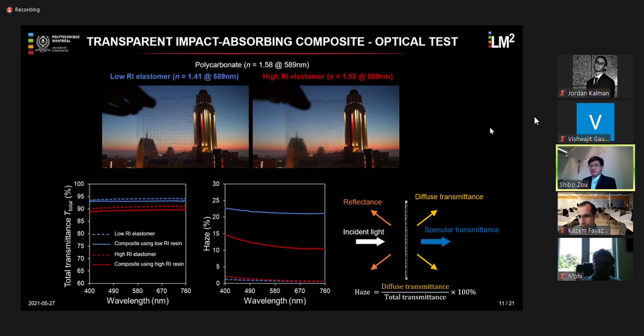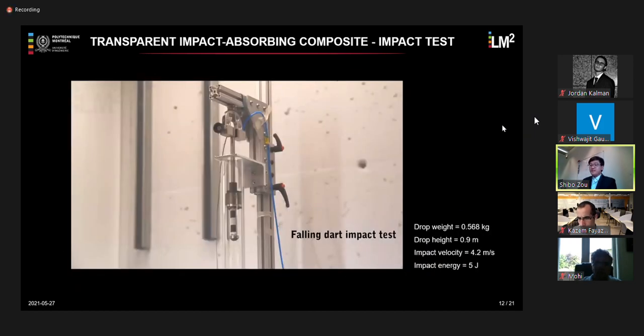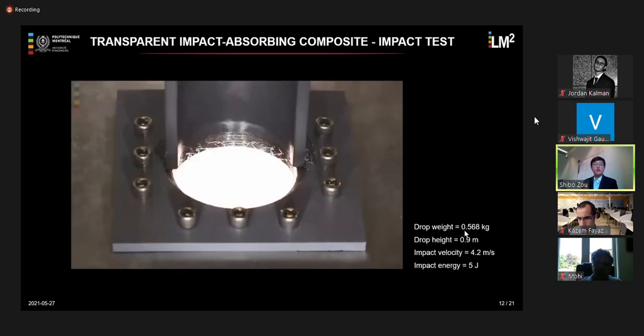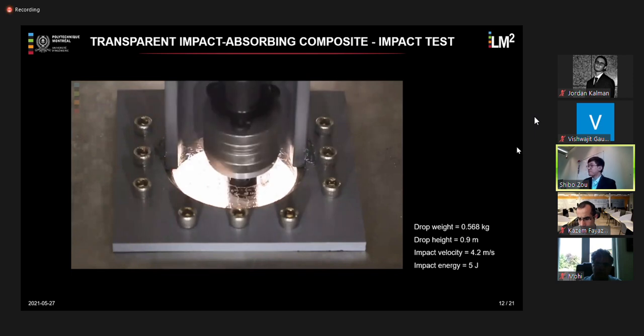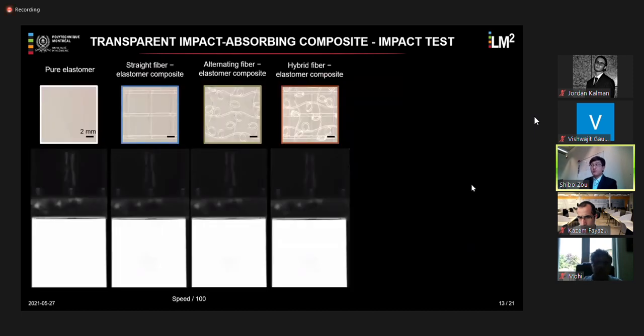So in the end, we finally tested the impact absorbing behavior of our composite on a falling dart impact tester. Here we use a drop height of around 0.9 meter, and the drop weight is a little bit more than half a kilo. This gives us an impact velocity of around 4.2 meter per second and an impact energy of around 5 joule. And we also use a high-speed camera to capture this.